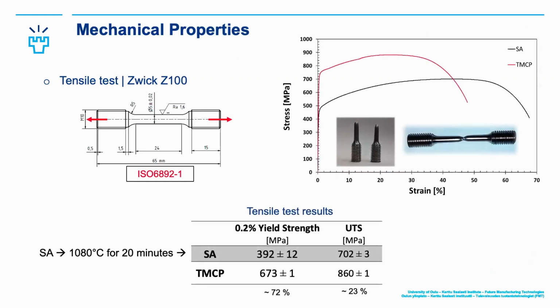We produced these samples from the TMCP plates according to the ISO. And we also produced one solution annealed plate for a reference or a comparison. And we could see here from the results that if we take the solution annealed case as a reference, we have an enhancement of 72% in the yield strength. So the yield strength reached 673 and the ultimate reached 860, with a relative enhancement of 23%.